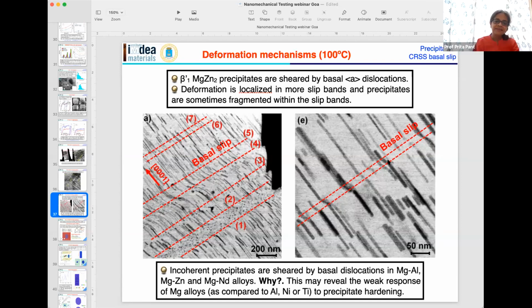So are we less likely to see this in more symmetric materials, or materials which have less inhomogeneity in Schmid factor, because there'll be other pathways? Yeah, so what makes magnesium particular for that is that the critical resolved shear stress for basal slip is much lower than for any other slip system. If you have FCC materials, of course, you have the same slip system but different planes, you are going to activate several of them. In the case of magnesium, very often you only activate one slip system, that is basal slip.